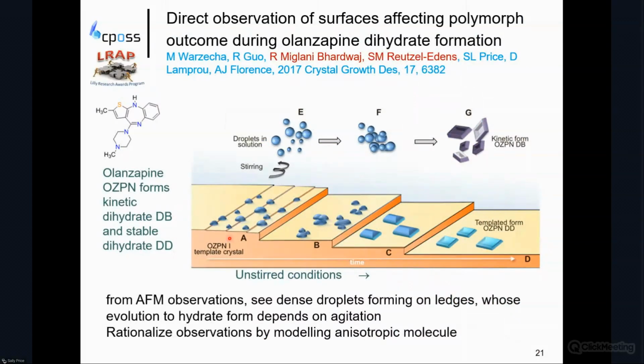This is an observation by atomic force microscopy of what happens to olanzapine when you put it in water. So what Monica first observed was that there were little hillocks growing on the edges on the surface of olanzapine form one. And with time, these hillocks evolved to orientated crystals of olanzapine dihydrate in the most stable polymorph D, nicely orientated and aligned.